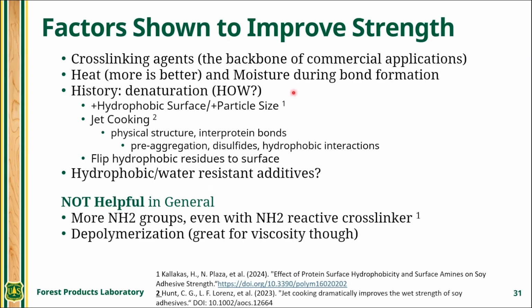History. So, what is the state of the protein as it's applied to the wood? We recently published a paper where hydrophobic surfaces seem to be correlated with better wet strength, which kind of makes sense because two proteins, if they have a lot of hydrophobic interactions, that would be a water-resistant way to transfer load between neighboring proteins. And what happens is if you have a lot of hydrophobic surfaces on the proteins and you're dispersing them in water, then you're going to end up with larger particles in the dispersion.